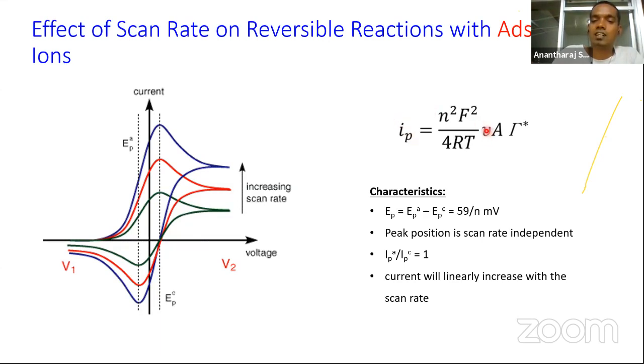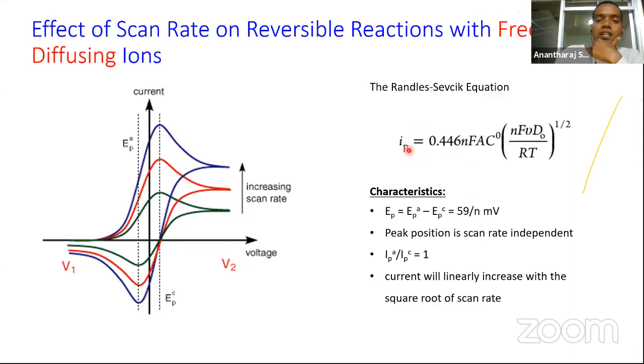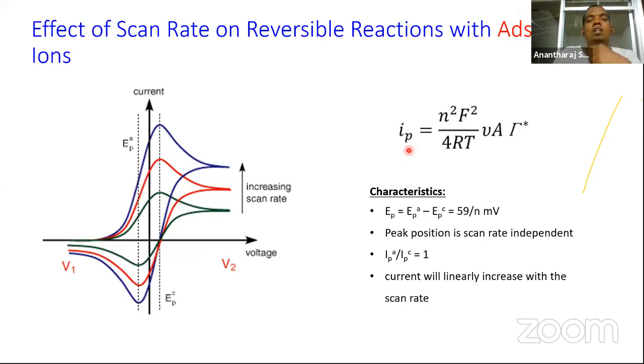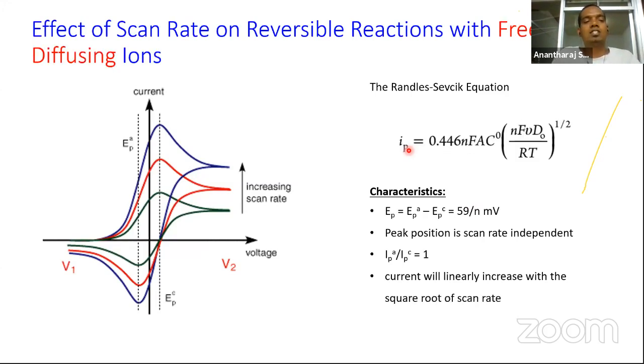In this case, the scan rate is not related with the square root form. Here it is related directly. So the peak current increases directly with the scan rate. So just by plotting these two equations, you can distinguish the nature of the reaction that is occurring. If you plot the peak current against the square root of scan rate, and it varies linearly, that is said to be occurring via freely diffusing ions.